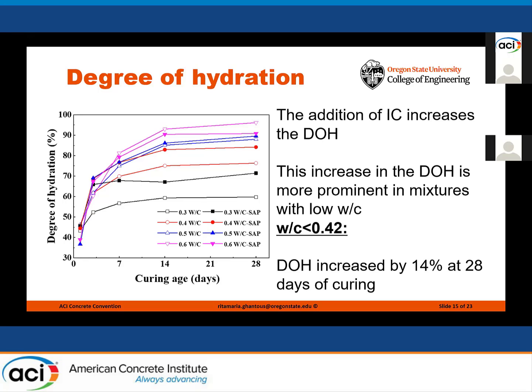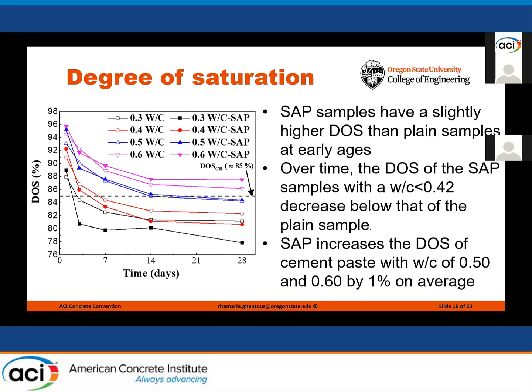And as we can see, if we look at the black curve and red curve, which are samples with low water to cement ratio below 0.42, we can see that the increase of the degree of hydration is more prominent than the other two mixtures with a higher water to cement ratio. For instance, for cement-based sample like the black and red one, the degree of hydration increased by 14% at 28 days of curing. So the takeaway from this slide is the benefit of internal curing is more visible in cement-based sample with low water to cement ratio. That's also visible in the degree of saturation measurements.